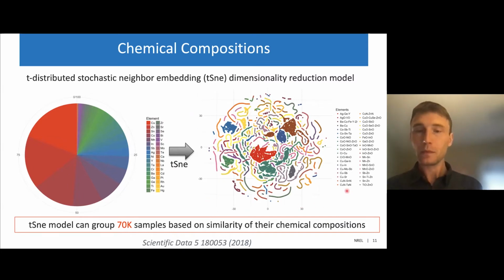just 2. So here you can see that in this type of analysis, many of our materials, different combinations of elements, form these types of lines, and the others form clouds. Lines correspond to pseudo-binary composition spread. For example, if you deposit copper oxide and zirconium oxide in a gradient, we would have a line like this. Whereas some of the clouds here correspond to ternary composition spread, such as this zinc, titanium, tin oxide case that I was talking about earlier.